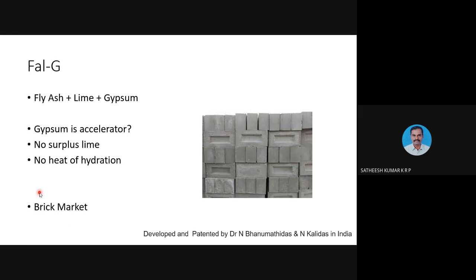The main ingredients of this FaL-G brick are FA, which stands for fly ash, L for lime, and G for gypsum. One of the most interesting characteristics of this combination of materials is that here gypsum is not a retarder. Gypsum acts as a retarder in conventional concrete or conventional cement, whereas in this combination, gypsum acts as an accelerator. This accelerates the reaction between fly ash and lime.